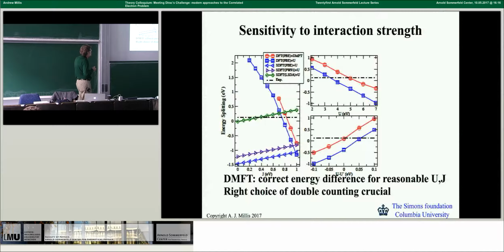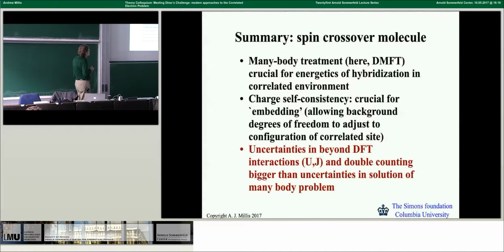This Hund's coupling is something that you can imagine determining, and in fact, this is about the right value, as we know by other reasons. The double counting is something for which there is not yet a good theory, and the energy difference depends sensitively upon it. So to summarize, what we learned from this spin crossover molecule is that a many-body treatment is crucial for the energetics of hybridization in a correlated environment, that charge self-consistency is crucial, and that the key source of error is the uncertainty in the beyond DFT interactions, and in particular in the double counting correction. These are bigger uncertainties than the ones in the solution to the many-body problem.